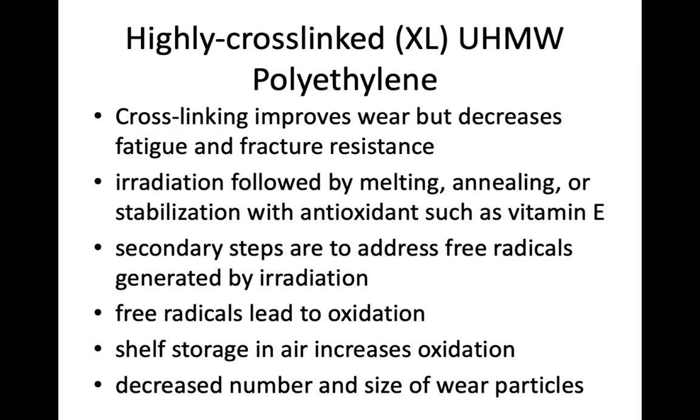Cross-linking occurs by irradiation followed by melting, annealing, or stabilization with antioxidants such as vitamin E. These secondary steps are used to address free radicals that are generated by irradiation. Free radicals lead to oxidation, and shelf storage in air increases oxidation. In general, highly cross-linked polyethylene has a decreased number and size of wear particles and subsequently less osteolysis.